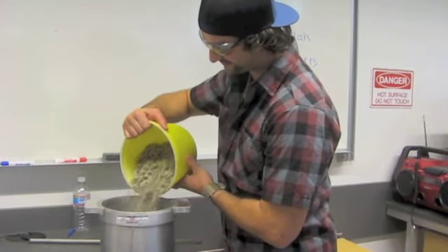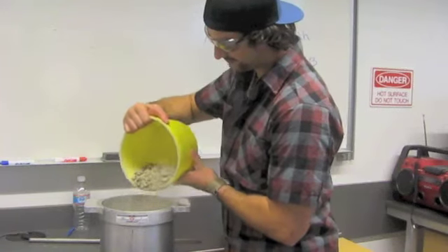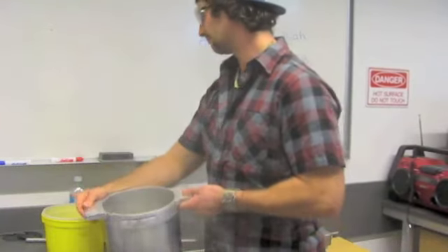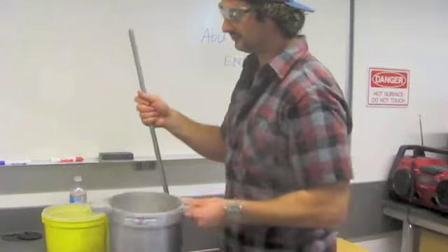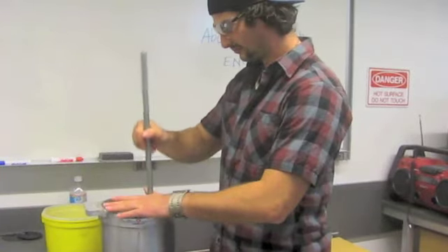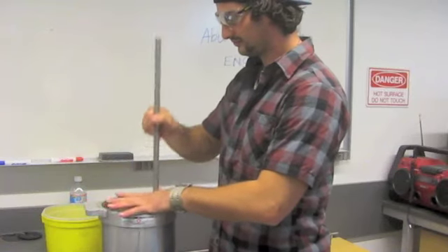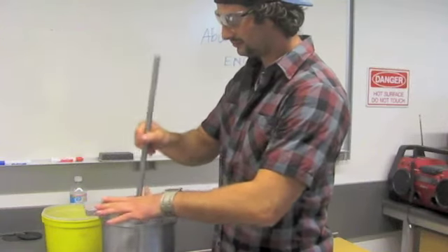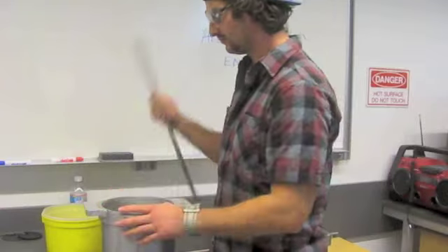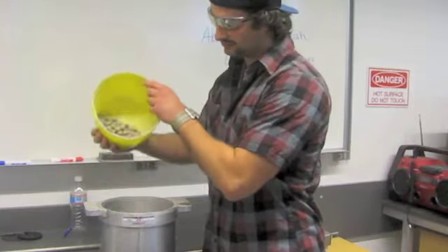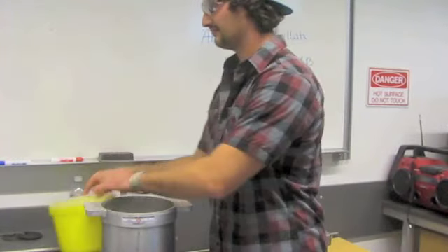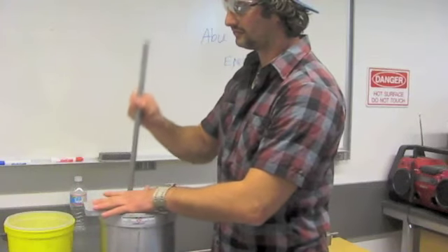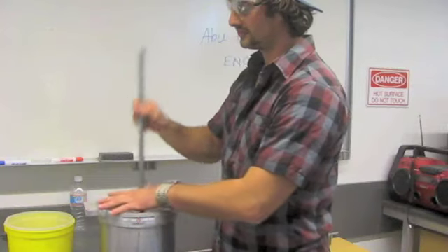Now, to determine the density, fill the measure with 1/3 of aggregate and level the surface with your fingers. Rod the layer of aggregate 25 strokes of the tamping rod evenly distributed over the surface. Add additional aggregate to the measure to 2/3 full level. Level with your fingers and rod again with 25 strokes of the tamping rod.